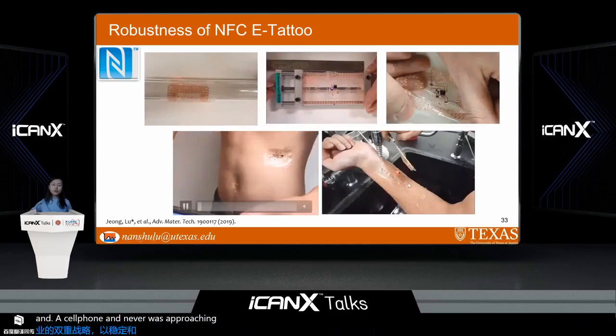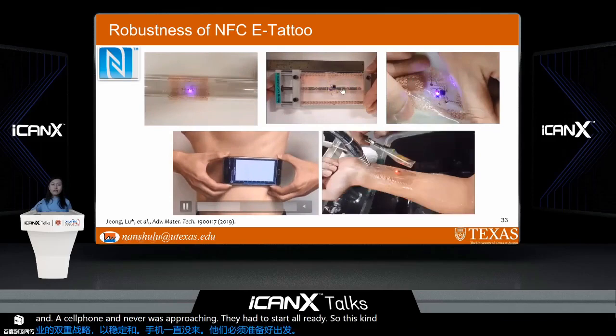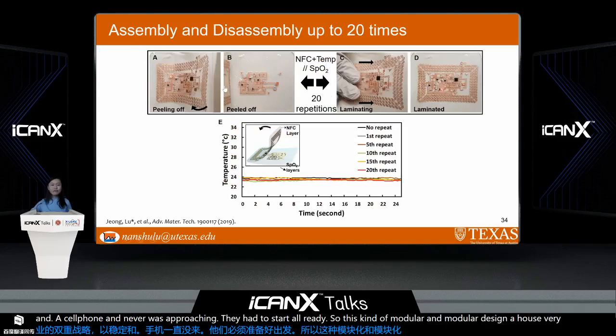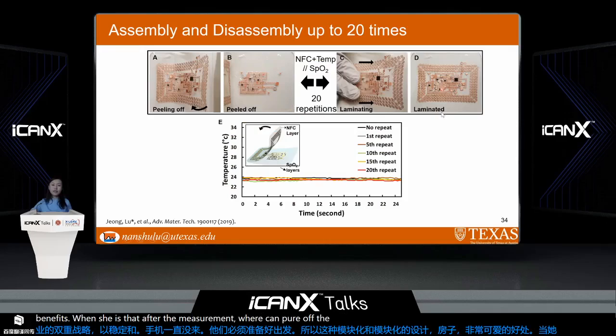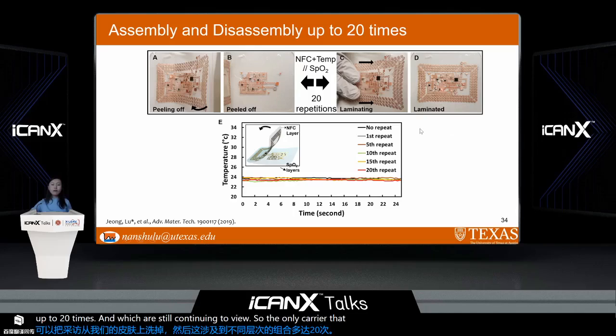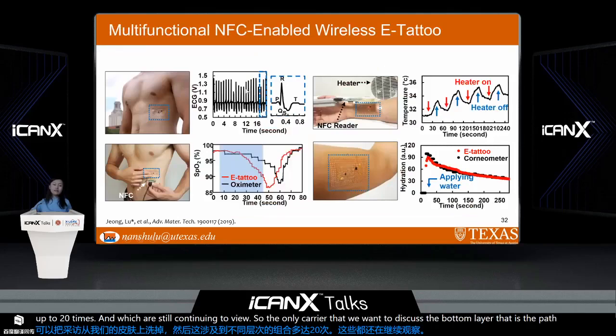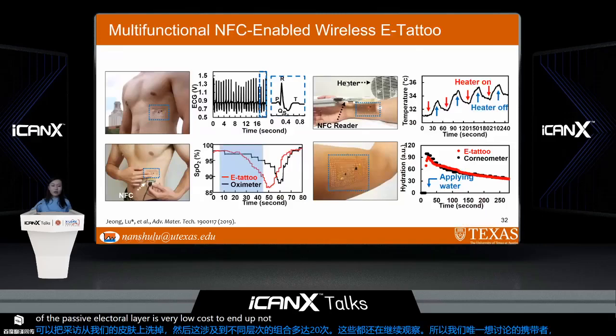So this kind of multi-layer and modular design has a very nice benefit, which is that after the measurement, we can peel off the e-tattoo from our skin and then disassemble those different layers. We can disassemble and assemble up to 20 times, and we can still continue to use this e-tattoo. So the only caveat is that we want to dispose the bottom layer, that is the passive electrode layer. This passive electrode layer is very low cost and not very troublesome to dispose.